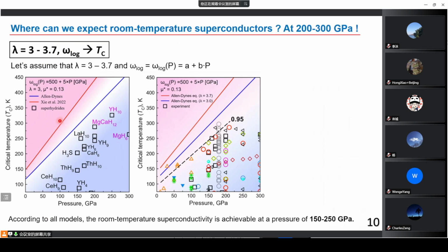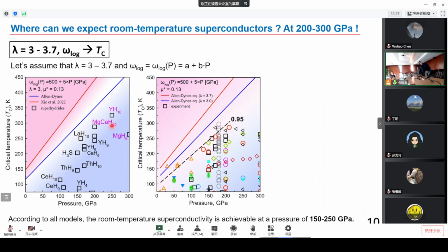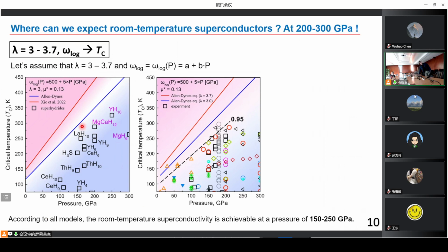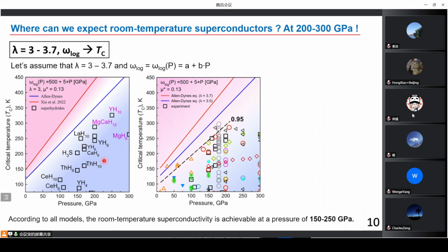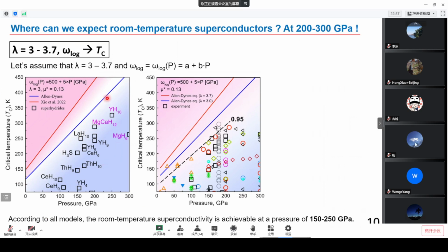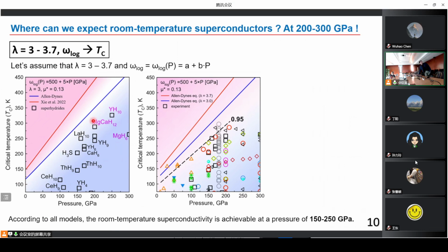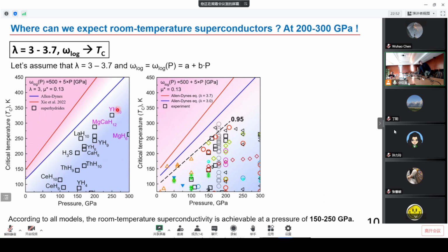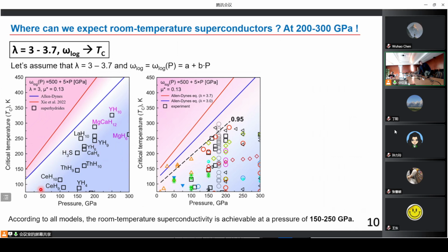C model, and you can see two lines, red and blue. Most of the experimentally found hydrides are below them, but the correlation is quite clear. If you want to get higher TC, you need to go higher in pressure. You should increase pressure. But you see that the experimental results are actually below the theoretically predicted line. So we are not so close. We should not be very positive. We should be a little bit less optimistic than the model gives us. Those models give us data.